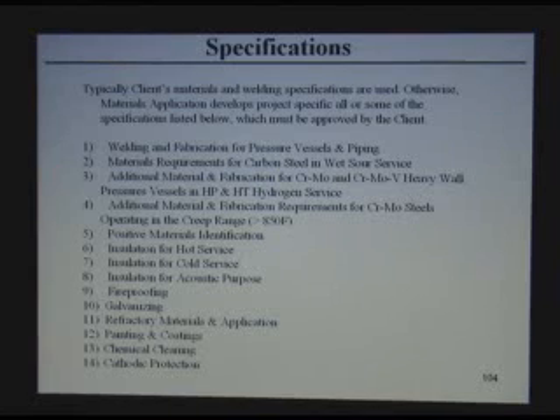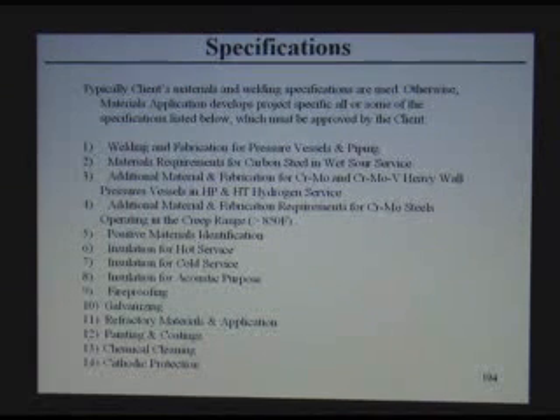We specify material requirements for wet sour service. Carbon steel, if you buy regular carbon steel, probably it will crack right away. But there are special steels, special chemistry, special production, how they make them, how to inspect them, how to heat treat them, equipment, how to produce them. We have to specify to avoid wet sour corrosion problems. For chrome moly steels, as I mentioned before, they are subject to temper embrittlement, and there are standards to specify them. And also, in addition, there are client requirements. And we can specify what is needed in the chemistry, what is needed on testing, what is needed on how to produce the steel, how to weld this equipment, and what kind of inspection you need after fabrication.